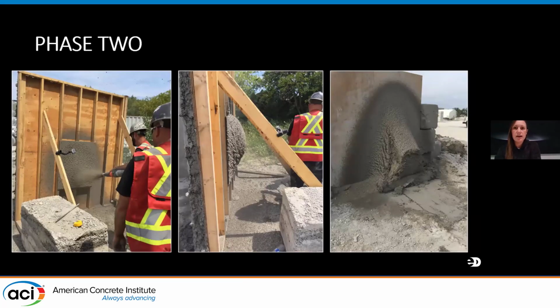Non-standardized tests, we did a Beehive test. I forgot to mention we had Rusty Morgan come and help advise on a bunch of this extra testing that we've done. But a Beehive test was performed. This is a procedure in which the shotcrete mixture is shot onto a vertically oriented piece of plywood, laminated panel. And the performance is measured by recording the thickness of the material that remains adhered to the panel before sloughing or falling off occurs. The greater the thickness of the beehive before sloughing, the higher the degree of thixotropy of the applied shotcrete, and the greater the adhesion and cohesion.